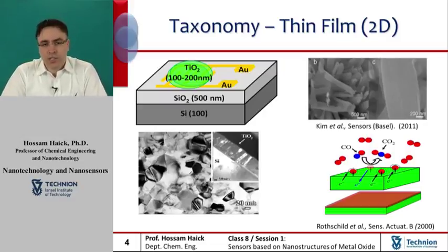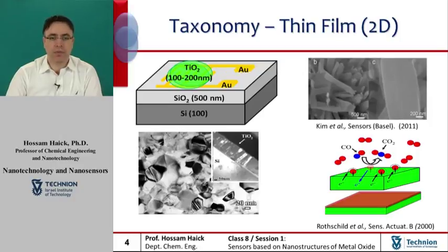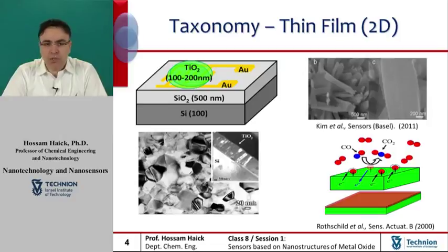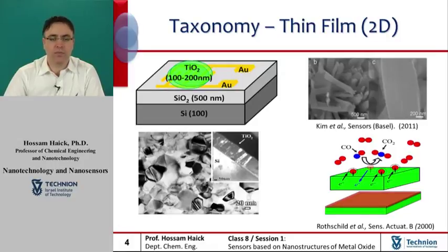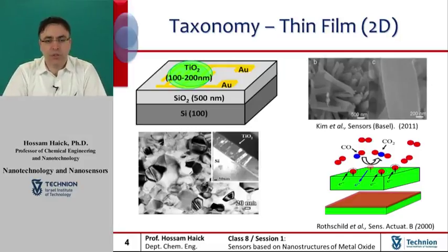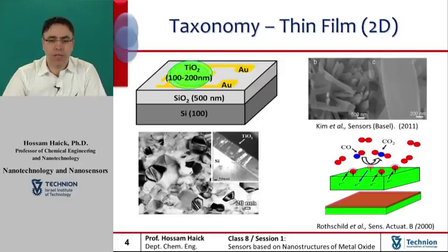The suggested sensing mechanism in this case is divided into two main stages. During the first stage, chemisorption of oxygen on the surface of titanium dioxide is followed by kinetics, where the change in surface adsorbate concentration with time follows a logarithmic reaction. Following surface adsorption, the second stage involves diffusion of the oxygen into the reduced non-stoichiometric titanium dioxide film, giving rise to an oxidized layer growth with relatively low electrical conductivity.